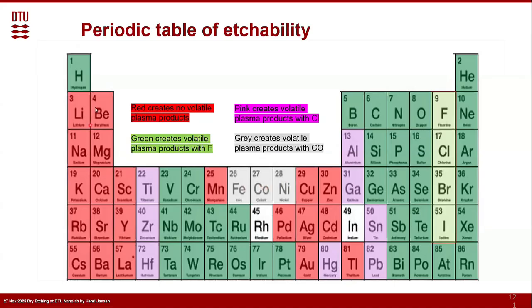The red ones, though, will never work. So the boiling temperature is so high that the vapor pressure is practically zero. So if you have a compound, the quick and dirty way would be just look into this table. What is red will stay. And that means that the only way to get rid of them is sputtering by argon or whatever, with all the dimensional effects. Let's say that it will start to contaminate your reactive ion etch tool, or create profiles which are questionable with respect to whether you would really like that.